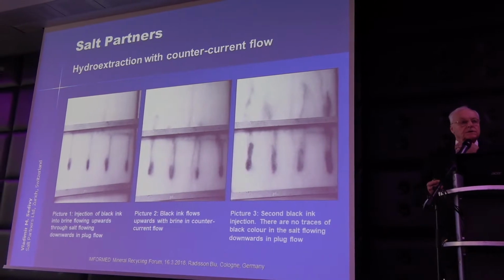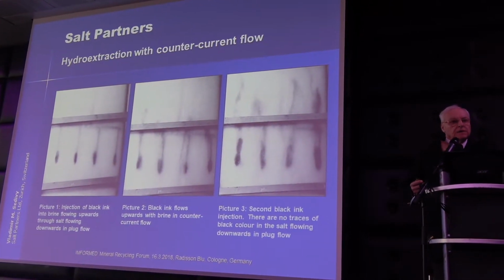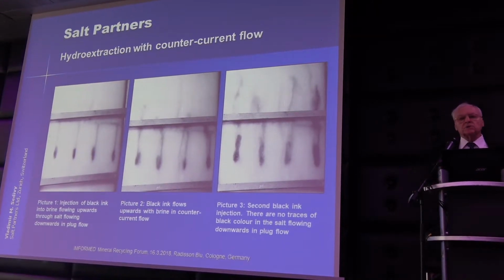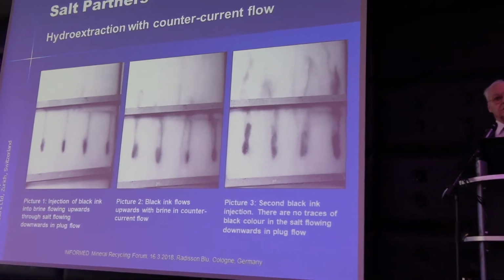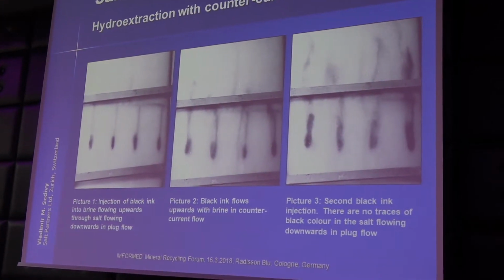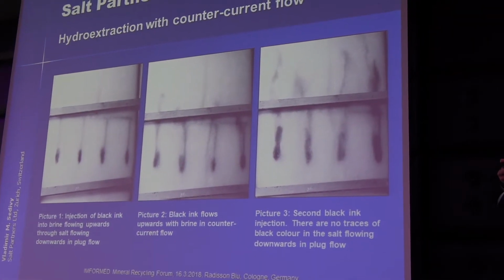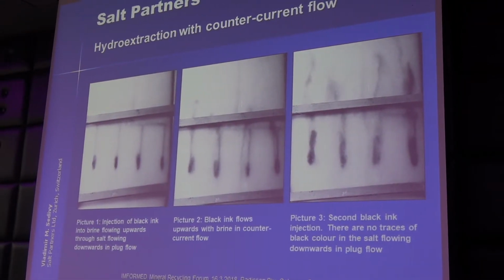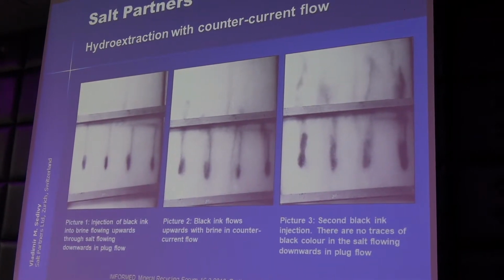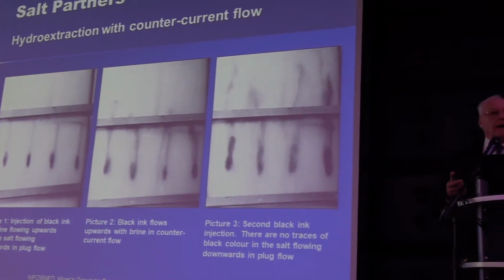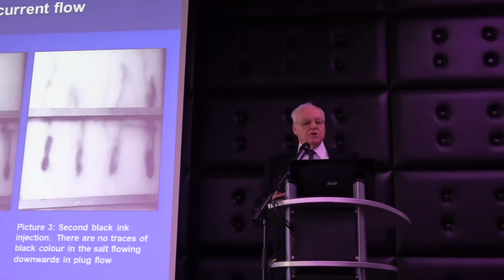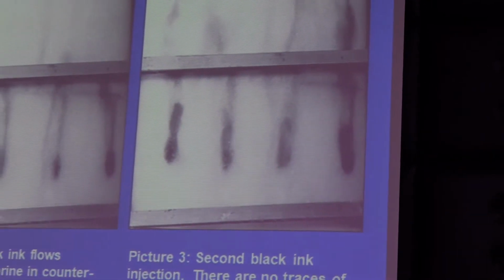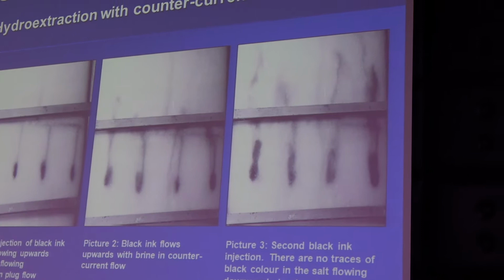This shows some development of the countercurrent. The countercurrent is not easy. It's actually rather difficult to do, because if the conditions are not correct, then the countercurrent flow goes by channels, and there is a channeling of impurities with the solids in the downflow, and a bypass through channels of the upflow. What you see here in white is solid salt crystals flowing down, and the black spots are brine that is colored with black ink to make it visible.